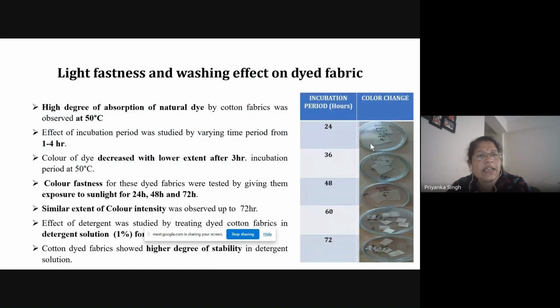Similarly, we have studied light fastness in the presence of natural sunlight. After incubating our dyed fabrics for up to 72 hours, we have found very little color variation. Color intensity is almost the same. We have found maximum color stability up to 4 hours, so this is the optimum period for which we can dry this cotton fabric in the sunlight.